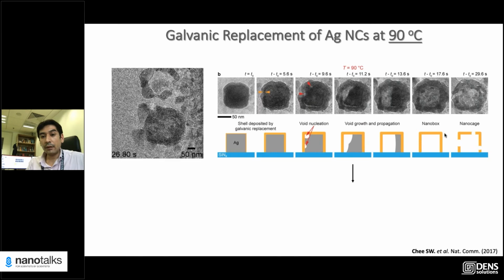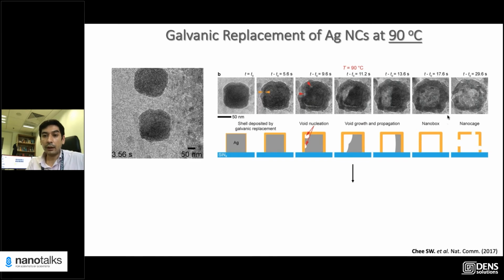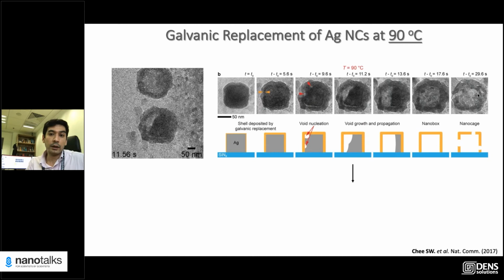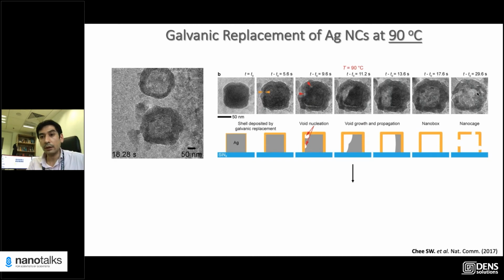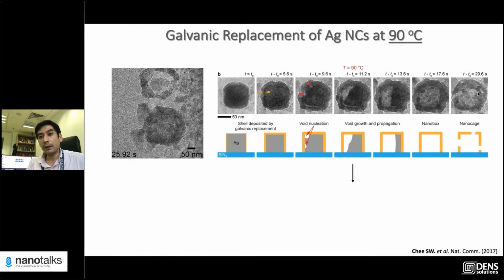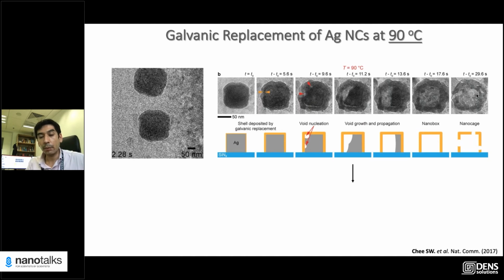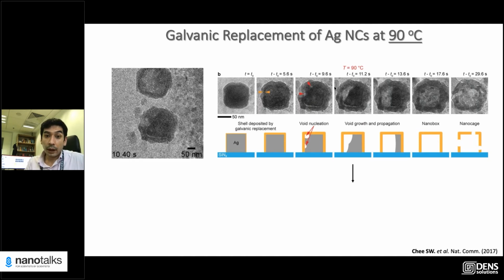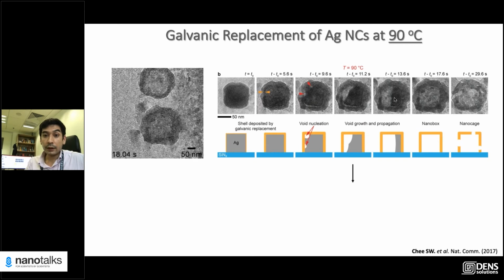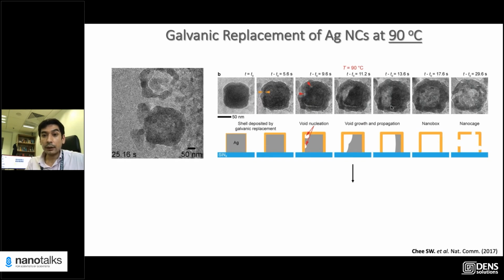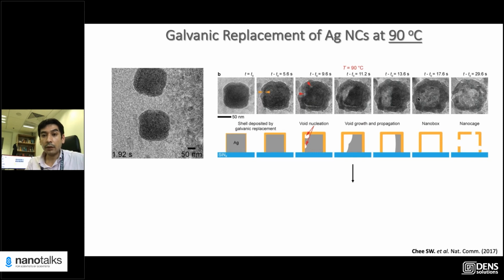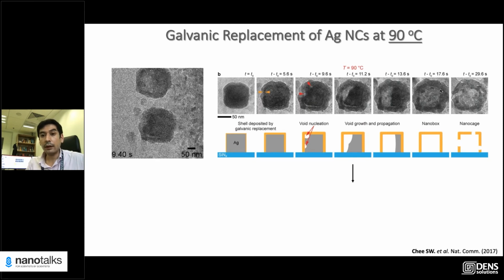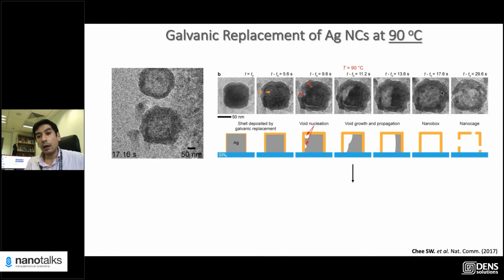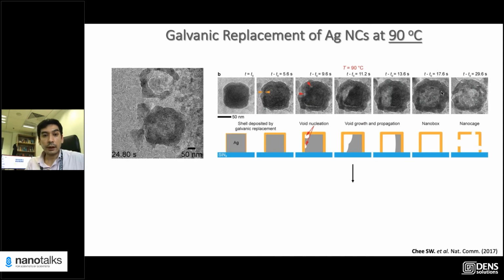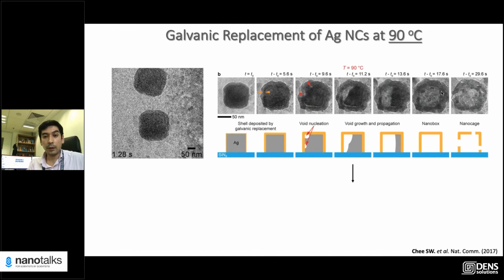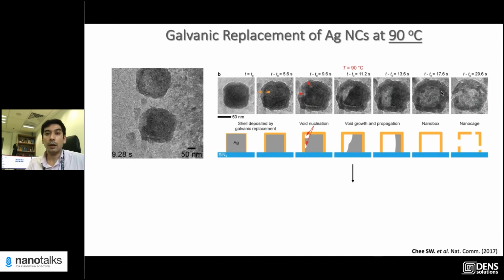But what we see is formation of the nanobox, and at the later stages, when the whole structure starts decomposing, we see clearly holes or pits forming on the surface of the structure. But at the initial part of the reaction, as this silver is getting eaten away and diffusing out, we do not detect any visible pits on the surface, as I alluded to earlier from a basic description of the galvanic replacement reaction.